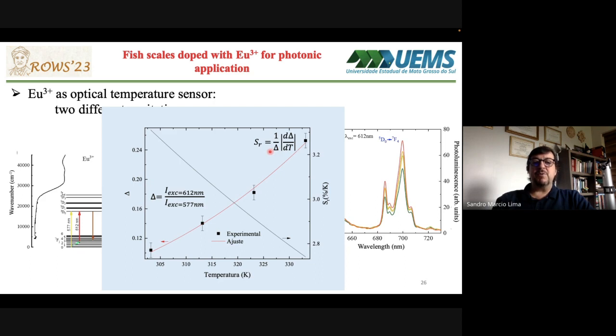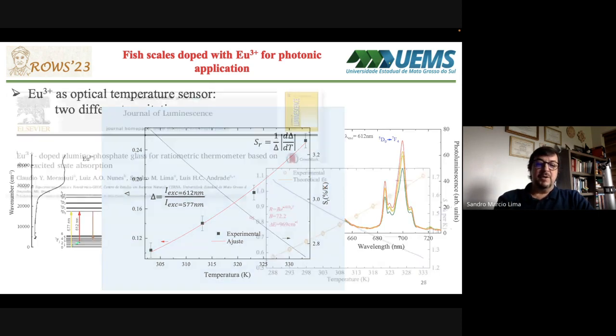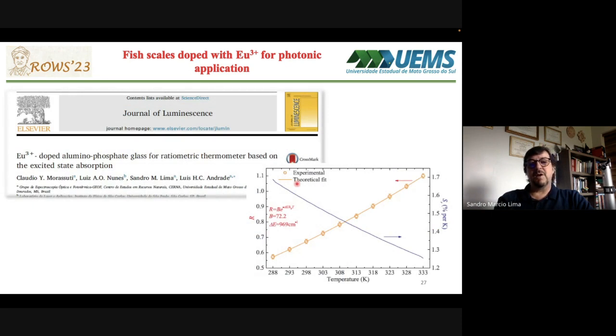In this case, we calculate how many percent the fluorescence signal intensity changes per unit of temperature. By the figure, we found a relative sensitivity around 3% per Kelvin, which can be considered high when compared with some values found in the literature. For instance, in this work, our own group registered a maximum of 1.7% per Kelvin at 333 Kelvin in europium 3+ doped aluminum phosphate glass.